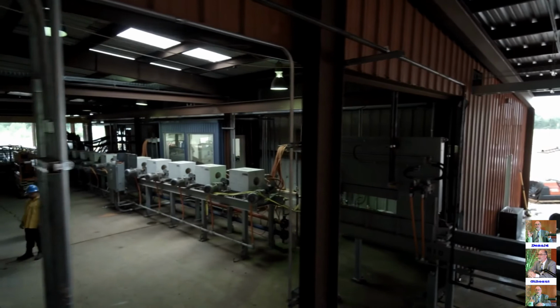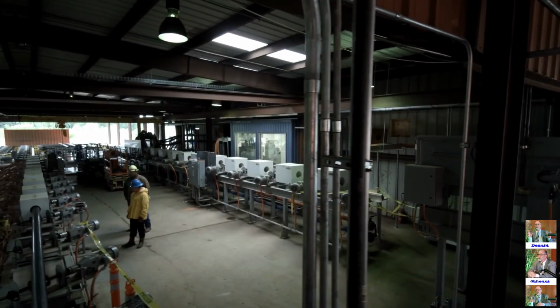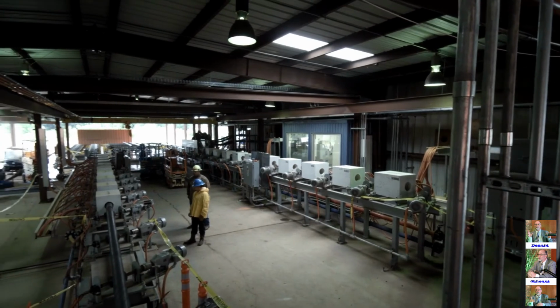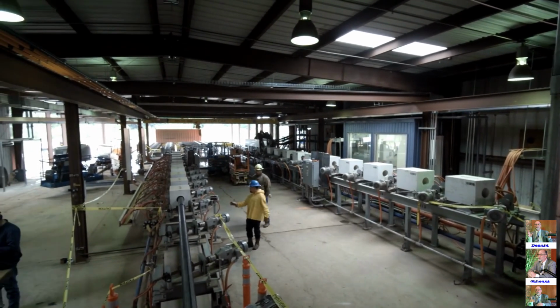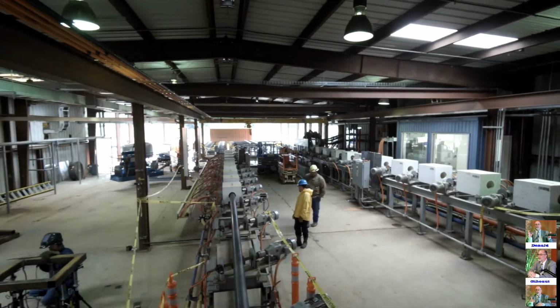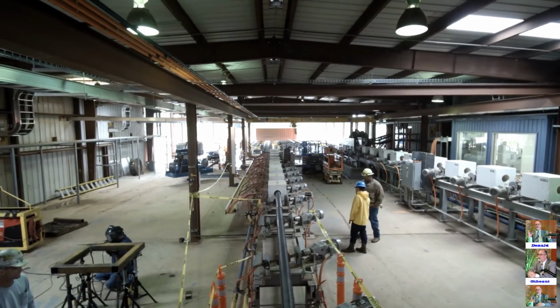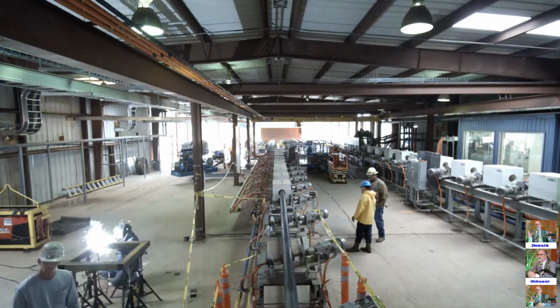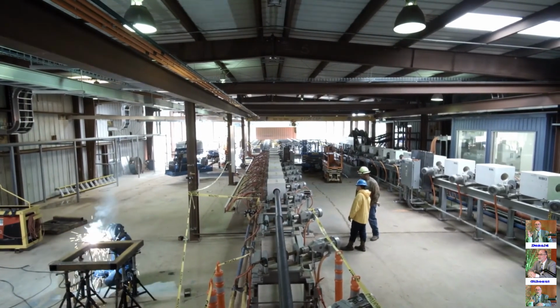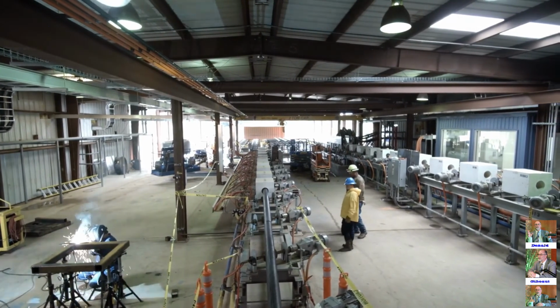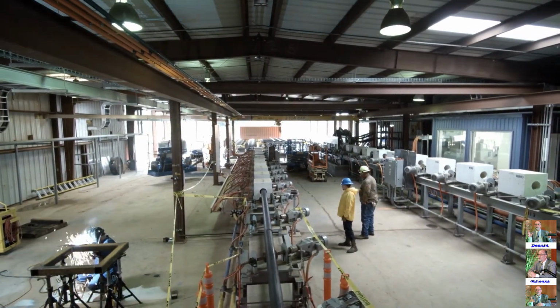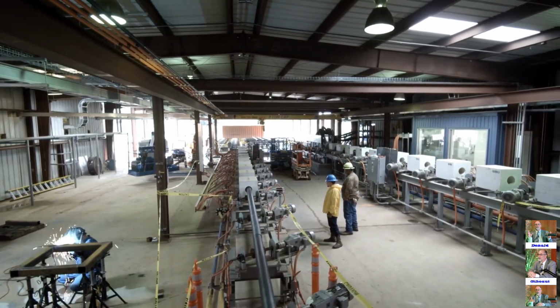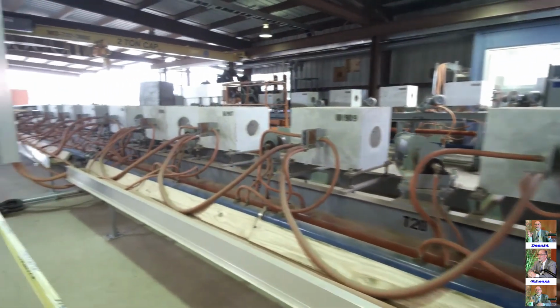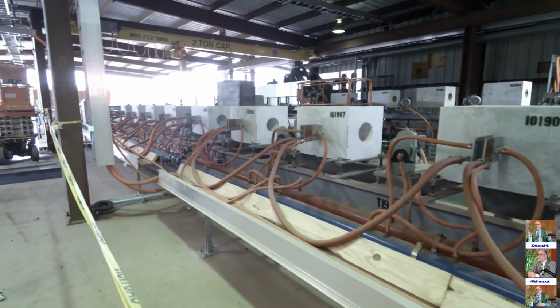We'll get a little bit closer look up here, but this is the austenitized section. The blue building, or the blue room to the right, is the operator control panel. What's directly below you here is the temper line. It's a U-shaped line. And as you can see here, the pipe is butted very nicely coming out and all the way through the induction coils, which we talked about earlier was critical to the uniformity. If that gap gets too broad, you're going to do a current crowding and overheat the ends. Here's the temper line, just daisy chain the water-cooled cables together in parallel series arrangements.